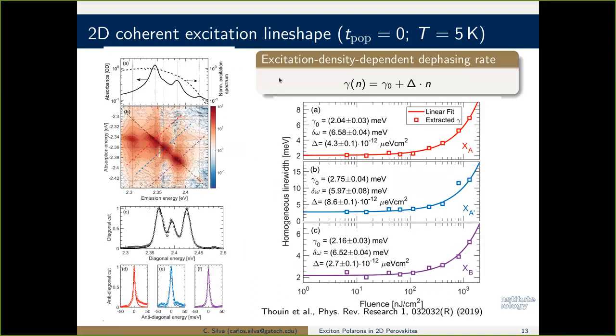I do my line shape analysis, and I say that the dephasing is this gamma. That's what loses the macroscopic phase coherence that I talked about when I described the experiment briefly. The dephasing has an intrinsic part. Basically, what's the garbage in my sample? What are the defects? Of course, electron-phonon coupling is intrinsic, but through phonons, through scattering with defects, whatever, there's an intrinsic dephasing rate that is just my sample. How good is my sample? But there's also a component that depends on density. N is the exciton density.